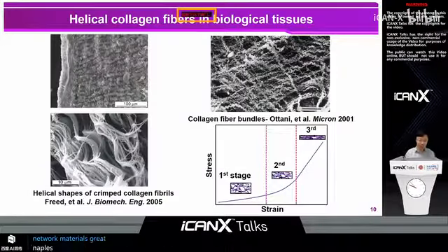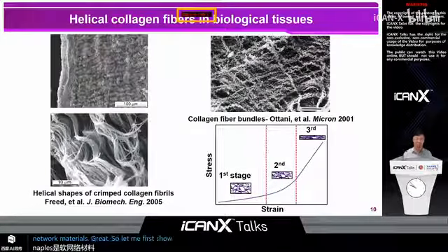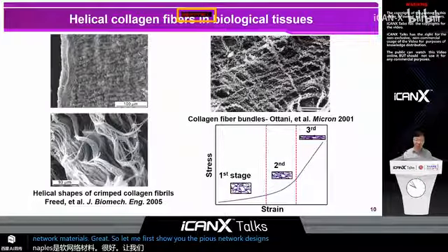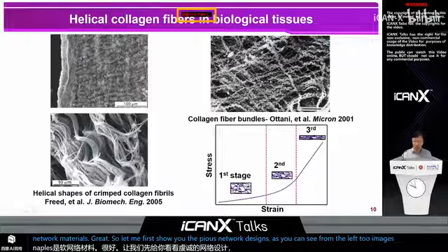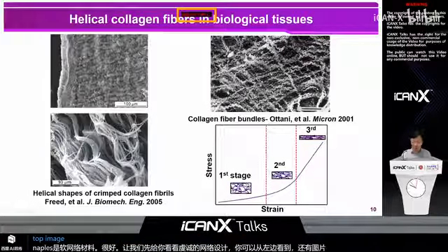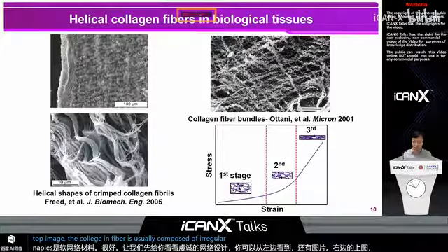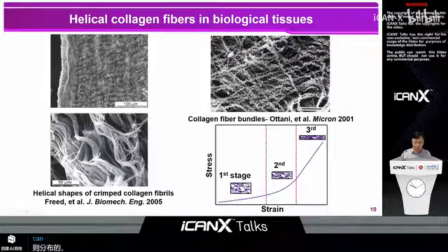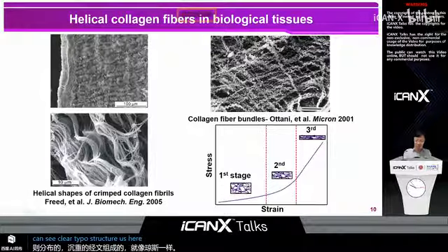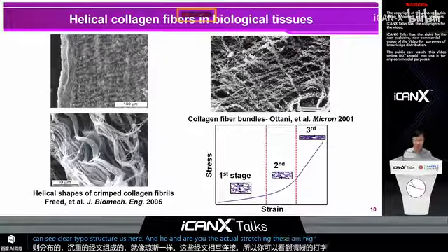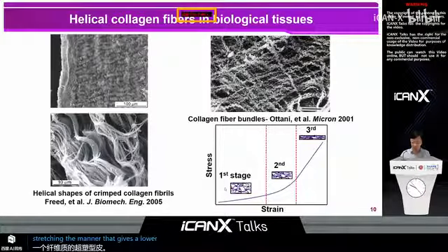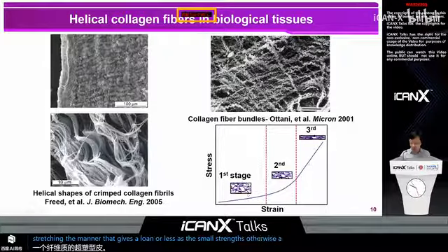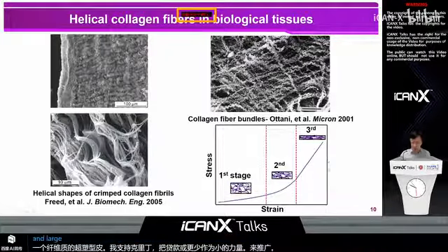Great. So let me first show you the bio-inspired network designs. As you can see from the left two images and the right top image, the collagen fiber is usually composed of irregularly distributed helical structures that are connected at certain joints. So you can see clear helical structures here. And under uniaxial stretching, this helical-shaped collagen fiber unfurls, straightens, and stretches in a manner that gives a low modulus at small strains, but with a sharp transition into the high modulus regime at large strains. So the result is a J-shaped stress strain curve, as you can see here.